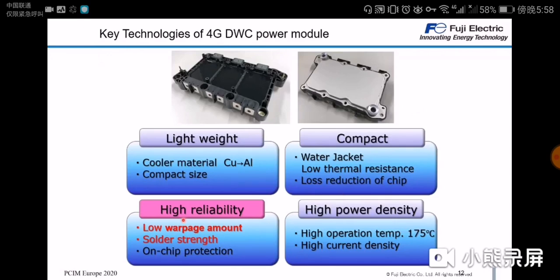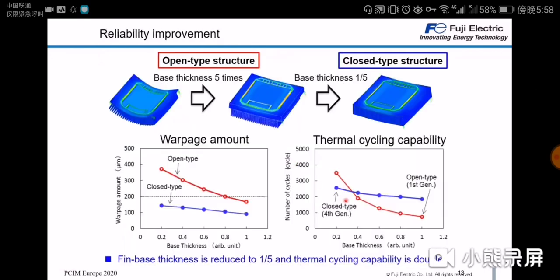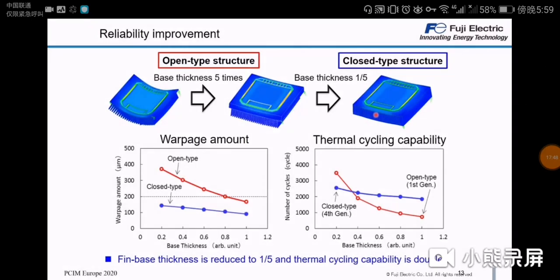Now we come to the reliability section. On this slide we can see the reliability improvement. In our first generation, as shown before, we used an open pin fin type structure, and therefore we needed a relatively thick fin base, thus increasing the thermal resistance. Now on the right side, in our fourth generation, we can have a very thin fin base without having a warpage issue. And this is because the top, the bottom and the fins are merged together to be like one part, so it's a very rigid construction.